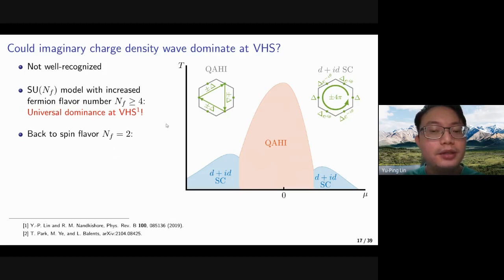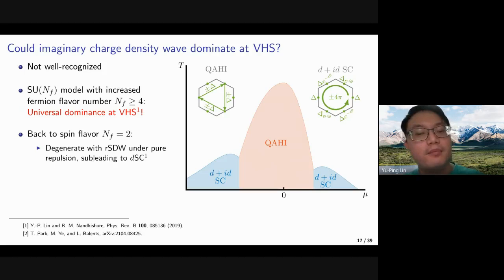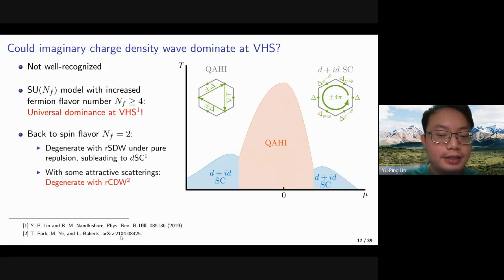And so we could also go back to the spin flavor N_f equal to 2. We also found that the imaginary charge density waves could be degenerate with the real spin density waves under pure repulsion, which are subleading to the d-wave superconductors. So this point was not pointed out by the previous research, and we found it, although we didn't mention it in our paper.